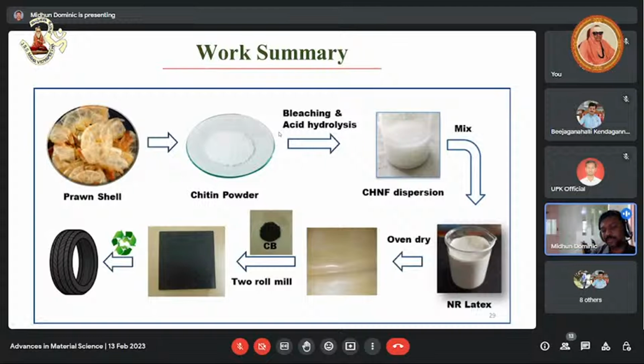So from the two papers, we could understand that even though we were able to decrease the rolling resistance, we have to compromise on the mechanical properties. So our aim is: is it possible to develop a new material with excellent mechanical properties and low rolling resistance? So we prepared chitin powder from prawn shell by alkali treatment followed by bleaching. This chitin is acid hydrolyzed using oxalic acid and steam exploded, and we get chitin nanofibers.